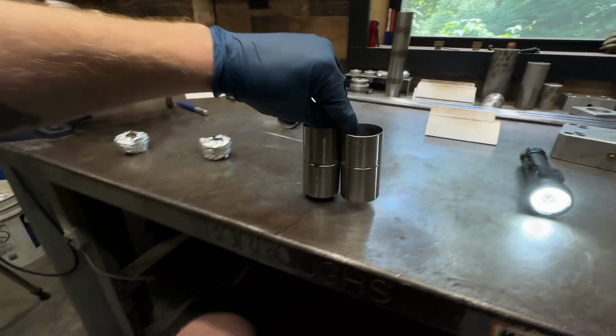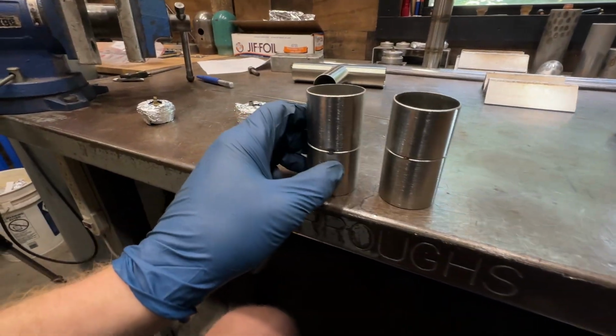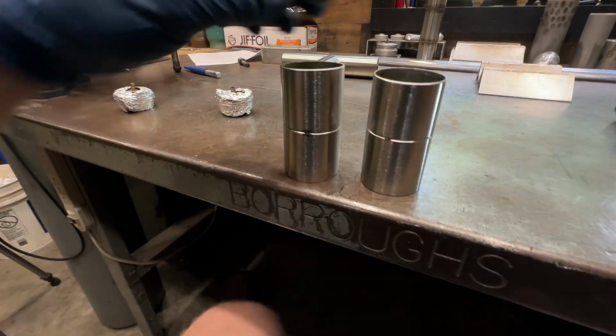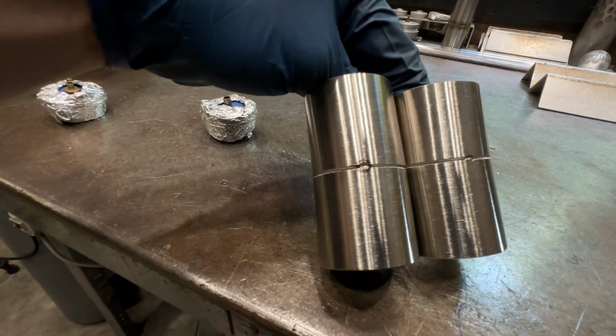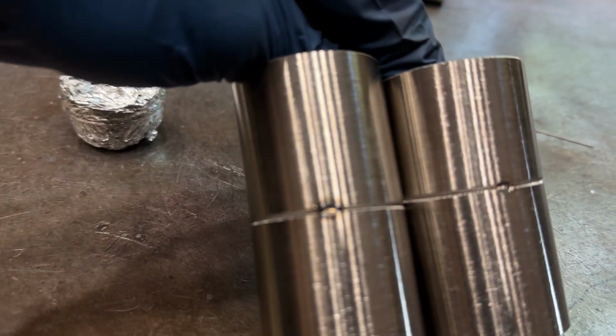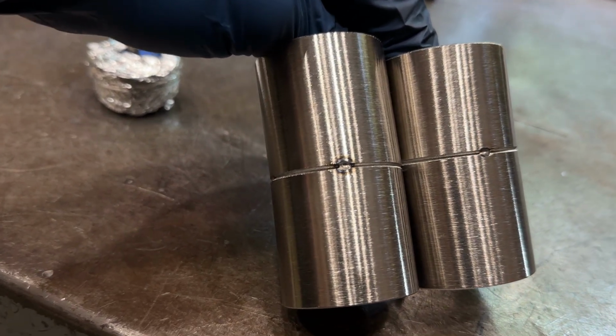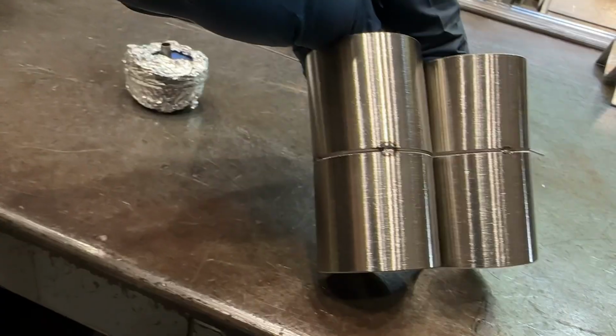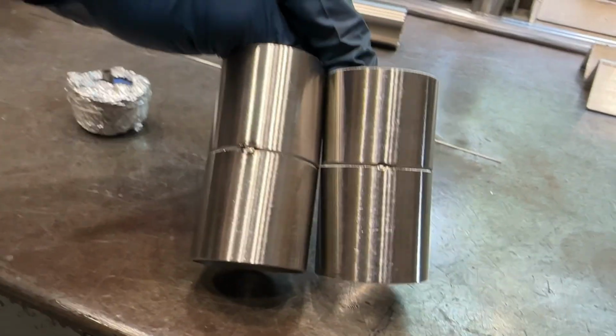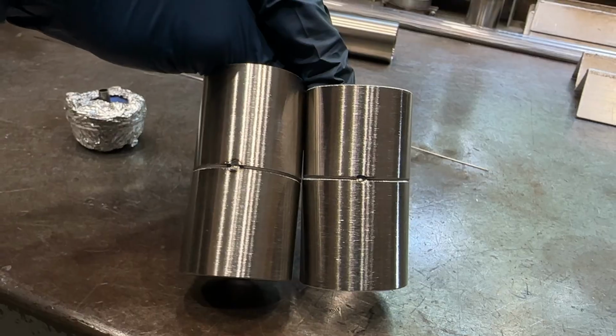Now, beyond the actual welds themselves, a tack weld is just a small weld, right? So tacking, it's necessary, at least in my opinion, to purge as well. So I cut a couple of other test pieces, and this one on the left is not purged, this one on the right is. We can see even just from the tacks, if we look at the exterior of it, the non-purged one on the left there, you can see some color around the tack that is no good. On the right, no color, which is good.